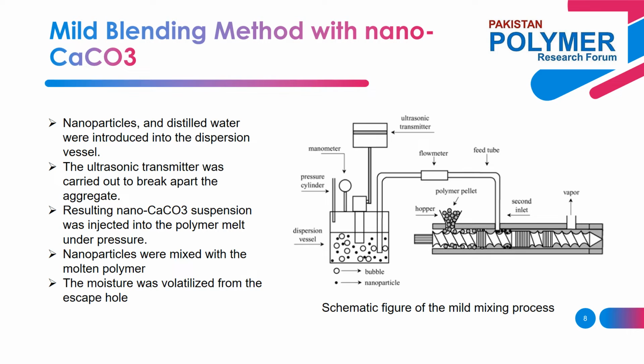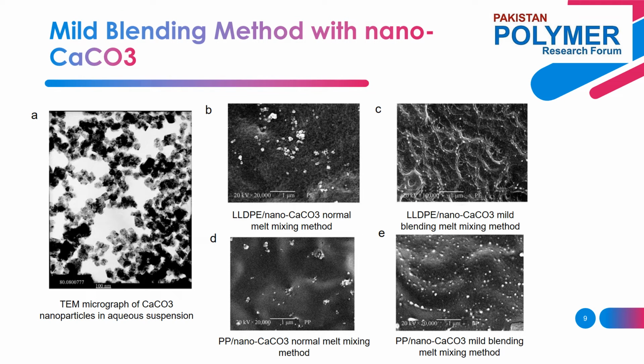A transmission electron micrograph of the nano calcium carbonate suspension is shown in figure A. Transmission electron microscopy analysis of the nano calcium carbonate suspension confirmed the presence of primary size dispersion of nanoparticles in the aqueous medium. The clear border of primary particles indicated that particles were cubic and diameter varied from 30 nanometers to 80 nanometers.